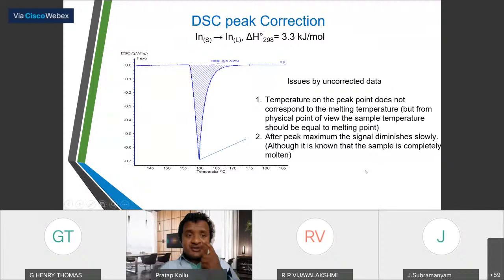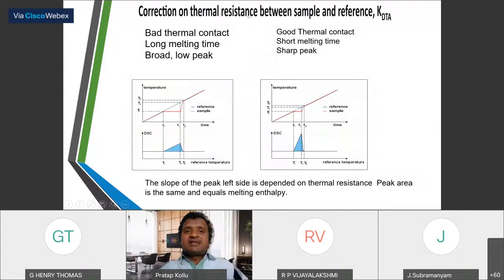Okay. So the temperature at the peak point does not correspond to the melting temperature. So look at here, it does not correspond to the melting temperature. So after the peak maximum, the signal diminishes slowly. So how do we correct it? So correction for thermal resistance between sample and reference. So if it is a bad thermal contact, the melting time will be long, and the peak will be broad, and it will have a less intense peak.